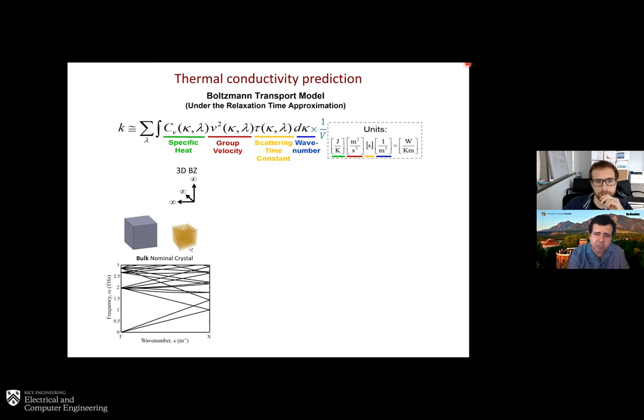So if you look closely, the thermal conductivity K is a summation of an integral over the Brillouin zone along the direction of interest. And in the integrand, there is a product of three quantities: the specific heat, the group velocity squared, and the scattering time constant, or the lifetime. So clearly, you can see that all of them are dependent on kappa and lambda there. So kappa is the wave vector, and lambda is the branch number, as shown there. And if you look at the band structure, we have many, many branches, and each branch will have a branch number.